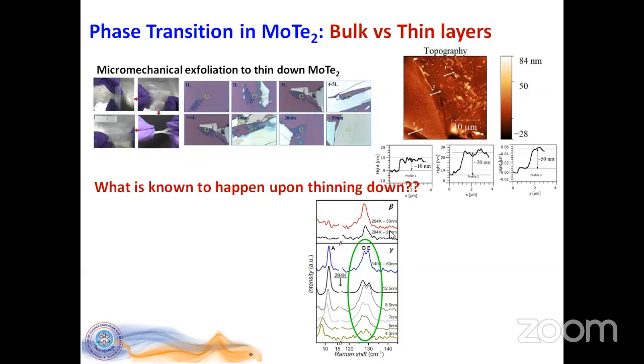But then as they thin down to below 20 nanometers, so here are examples that they have given, like below 12, 8, and so nanometer. As you can see, at room temperature itself, this particular mode splits into two components. So what it basically establishes is that even at room temperature, the MoTe2, when it is thinned down, gets stuck in the low temperature phase, which is the Weyl semi-metallic phase, okay? Or rather, I would say that it is the orthorhombic phase.